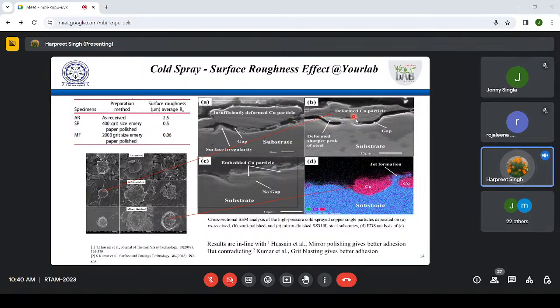So there were some gaps we saw in the SEM images. But when the surface was perfectly mirror polished, with this much roughness, we could get a very nice adhesion here. You can see copper and substrate, they are adhered very well. So this worked very nicely, and we could get very good adhesion strength when the roughness was at mirror polished